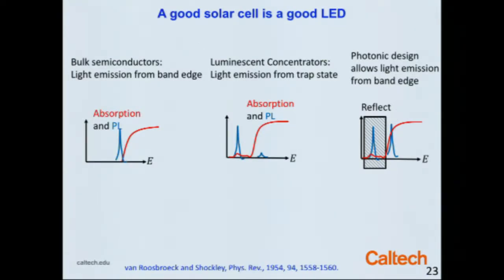Von Roosbroeck and Shockley basically worked out the physics of this, showing that this exponential decay in the absorption corresponds to an exponential increase in the concentration factor for luminescence photons that are downshifted by an energy delta E from the band edge.